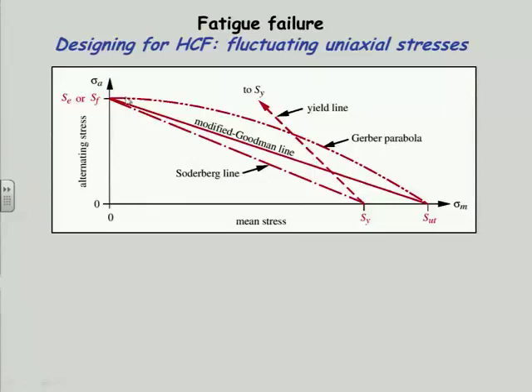As I said, Soderberg was very conservative, and he said, I'm going to avoid that problem by just ending my line at the yield strength of the material. And that Soderberg line is pretty much under the scatter completely, with some room to spare. So if you're very conservative, you can use the Soderberg. If you're moderate, use the Goodman.